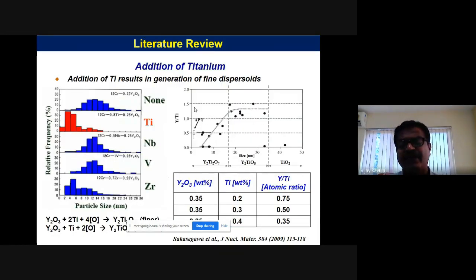Coming to the literature review on how oxide dispersion happens, yttria is very much used in this dispersion. When you want to refine the yttria oxide particles, people tried different element additions, and found that titanium refines the oxide particles to a fine stage, forming oxides like Y2Ti2O7 and Y2TiO5 particles. The finer one is Y2Ti2O7. People always look for formation of Y2Ti2O7 particles, and for that you need to maintain an atomic ratio, or a weight ratio.